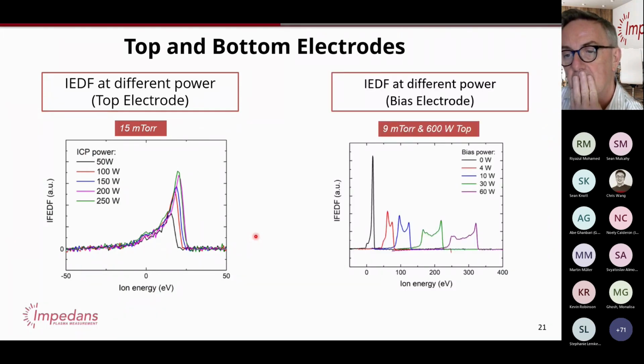There are three things actually that can impact the data. One is neutrals picking up charge from the collector plate. You can have radicals interacting with the collector plate, which is measuring the current. You can also have ultraviolet being emitted from the plasma, like a hydrogen plasma, they're all emitting lots of ultraviolet. If the energy is high enough, you'll also be producing secondary electron emission. But the good thing is those effects are constant. So what they generally do is cause a constant offset in the data.